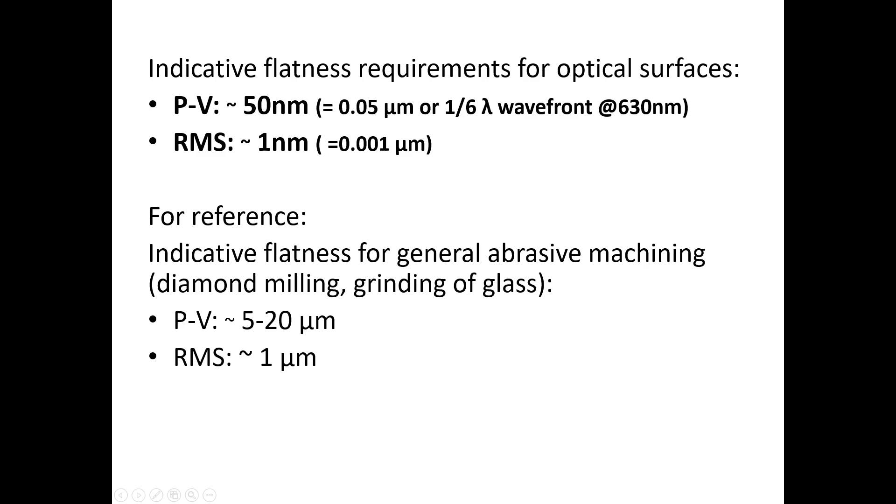But achieving the specs required for optics is not always easy. The flatness and smoothness specs are on quite a different level when compared to general machining methods such as milling and grinding. For a good optical surface, we want the accuracy to be in the nanometer range. So the peak to valley flatness should be in the order of let's say 50 nm, which is more than 100 times better than is achieved by machining.